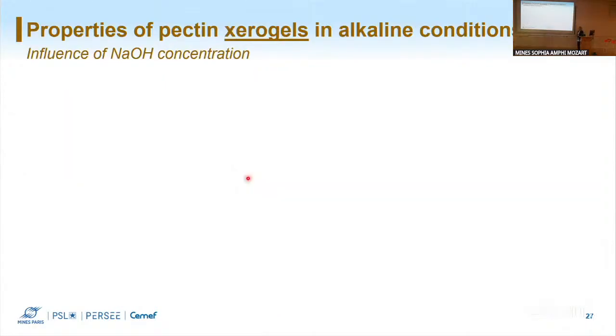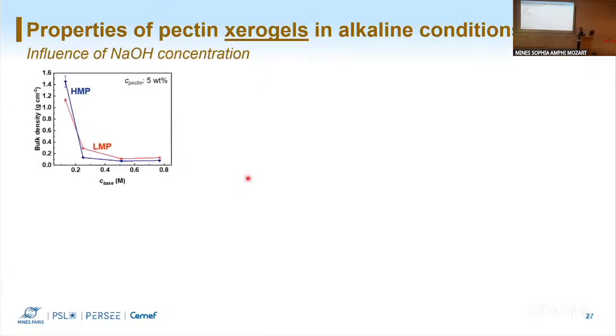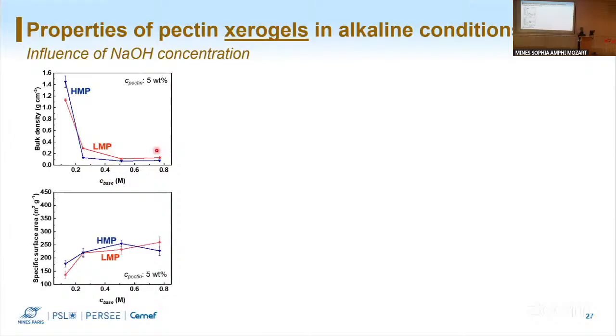Coming to the properties of the xerogels, so dried by evaporation, we see a huge effect on the bulk density, depending on the concentration of base. So again, high and low methoxypectin. When the concentration of base is very low, we have very, very high bulk density that is close to the density of pectin. And as we increase the base in our system, we reach values that are very low. Then the specific surface area starts again with lower values, and as we increase the base concentration, they reach values up to 270, 280.